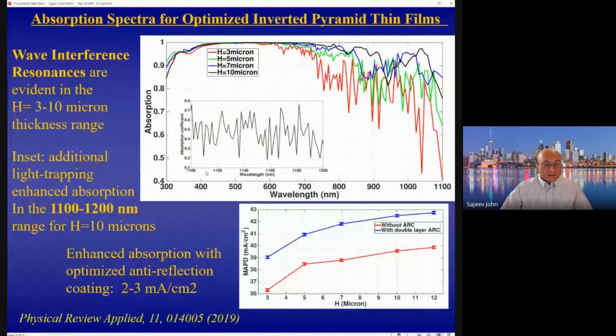And we can even extend this into the far region of the near infrared, from 1100 to 1200 nanometers, where the inset refers to the 10 micron thick structure, where again, due to these resonances, we're still absorbing about 40% of the sunlight in that range. And as I mentioned, if you add an anti-reflection coating on top of this inverted pyramid structure, you can typically gain an additional 2 to 3 milliamps per square centimeter. So this red curve is without anti-reflection coating, or ARC as we refer to it, and the blue curve is with the anti-reflection coating. And so here you see at 10 microns, we're up to about 42.5 or slightly higher milliamps per square centimeter.